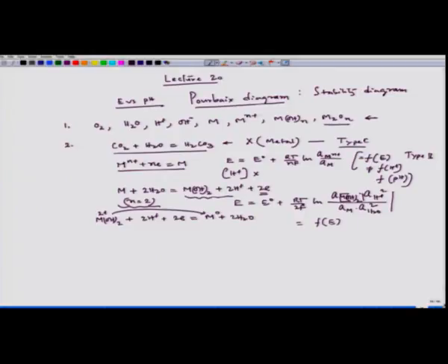So, this particular thing, if we consider it to be pure and solid, I can consider the activity to be 1, and if we consider it is pure water, the activity becomes 1. Metal, of course, is pure and activity 1. So, then this equation we can write in terms of E0 plus RT/2F ln activity of H plus.